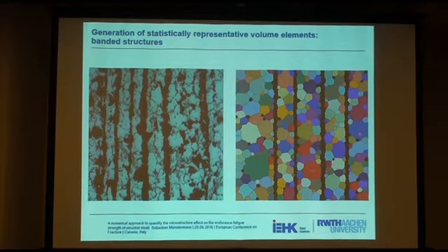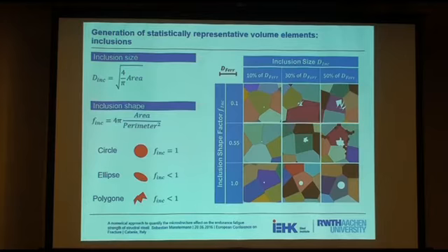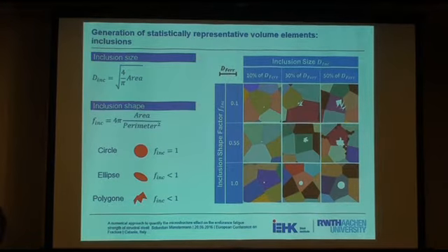Just to mention, we are also able to consider the elongations of these banded kinds of microstructures, which are quite often present in pearlitic steels. For fatigue investigations, this is really important. We also need to consider the inclusions. The inclusions are addressed on the one hand by their average diameter and on the other hand by their shape factor. The shape factor can vary between 0 and 1. If it is 1, then the inclusion has a circular shape, whereas a significantly smaller number than 1 means that there is a very polygonal shape of this inclusion. Also here, you will later see both the inclusion diameter and the inclusion shape.